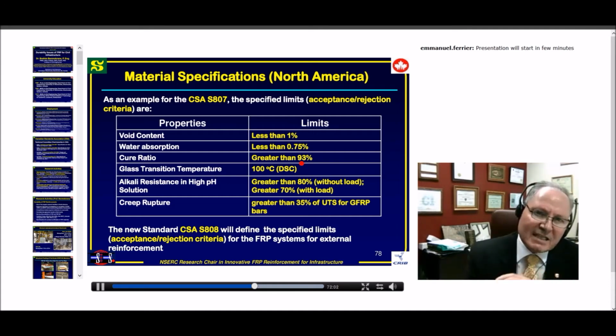And from this statistical analysis, based on the three products that we proved to be really durable in the field, we came out with this 80, 70, and so on. Maybe in the new edition, because now all the bars that were qualified and tested, I know at least 5 or 6 that went through the whole process. And most of them are getting, of course, a higher number, greater than 90%. So maybe we'll come out with a new number in the coming edition that we'll be preparing this year for the S807.